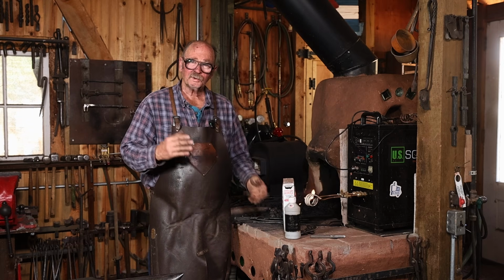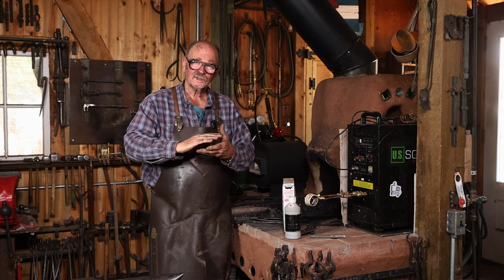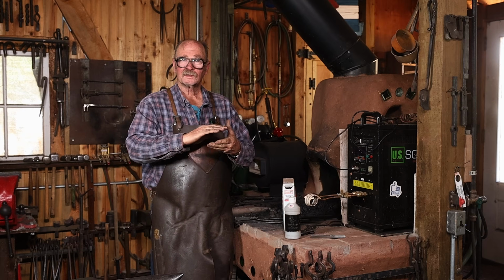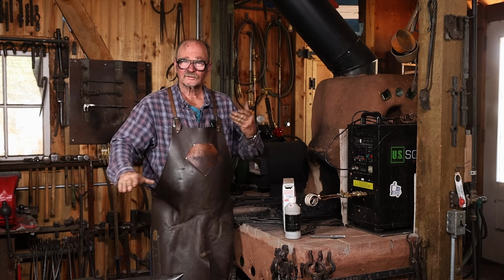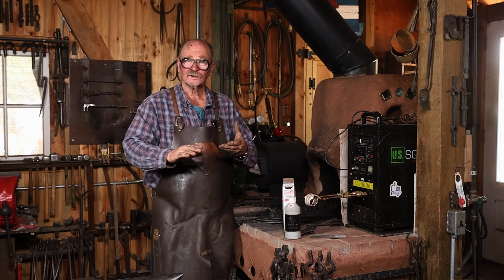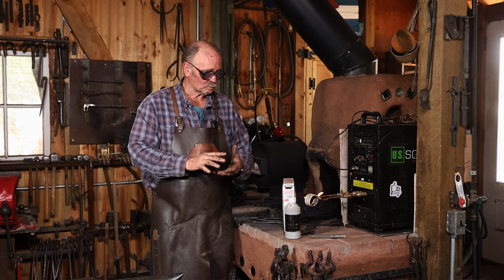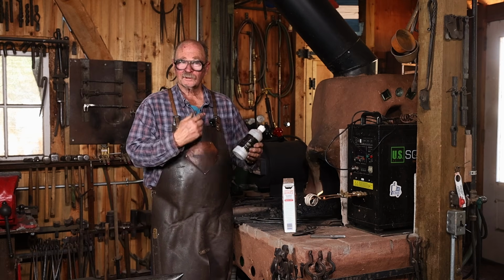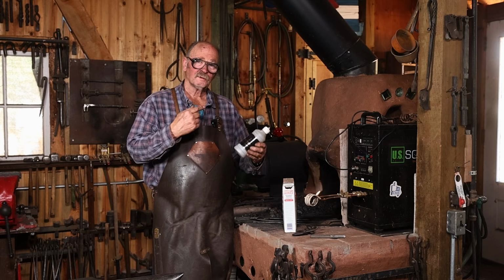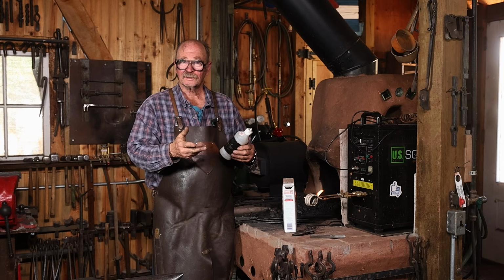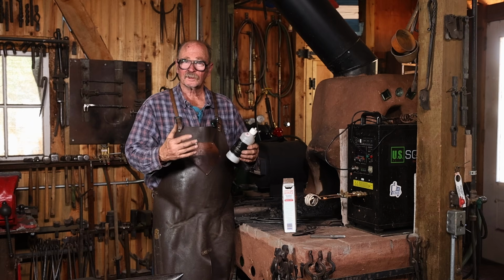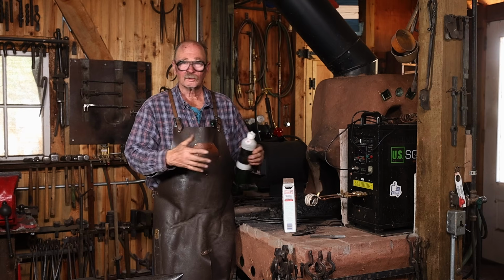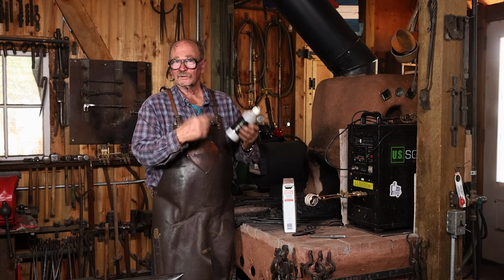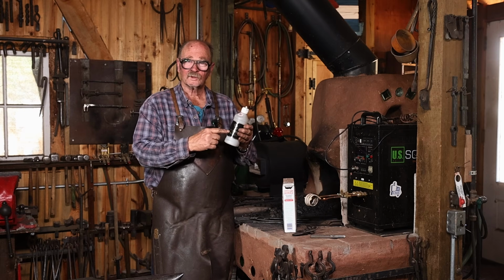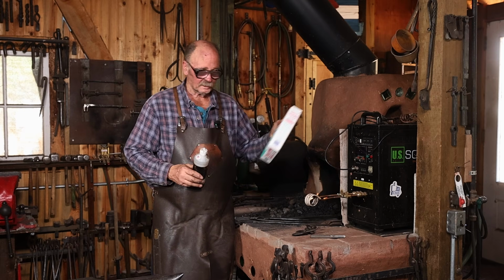But if you're doing a two-piece weld where you come together at the anvil, that slippery nature oftentimes means the first hammer blow, you're just sliding the pieces past each other, and it makes it really hard to get the weld to stick. Easy Weld and the Iron Mountain Flux are kind of tacky. The iron filings help with that, but for the scarf welds or the two-piece welds, drop tong welds, whatever you want to call it, I really prefer to use one of these commercial flux compounds over the borax.